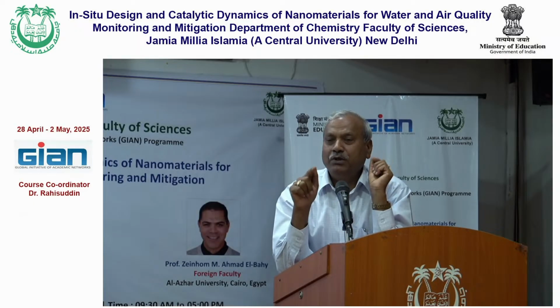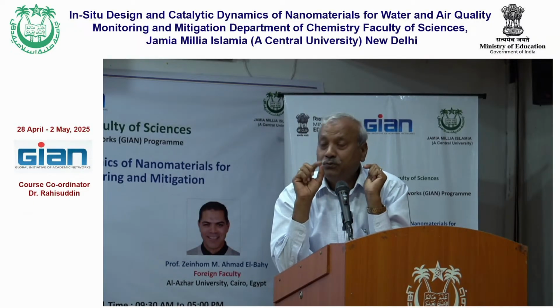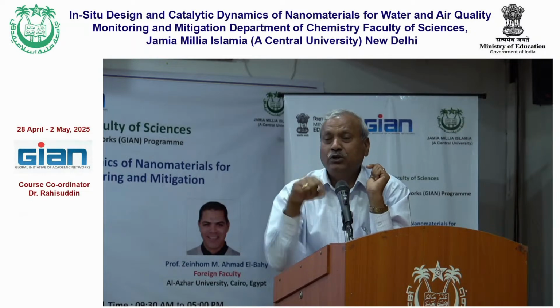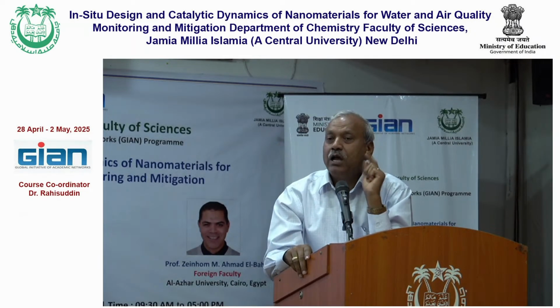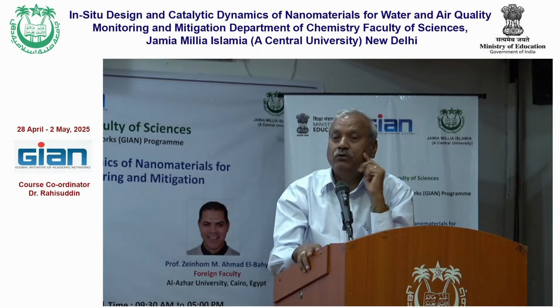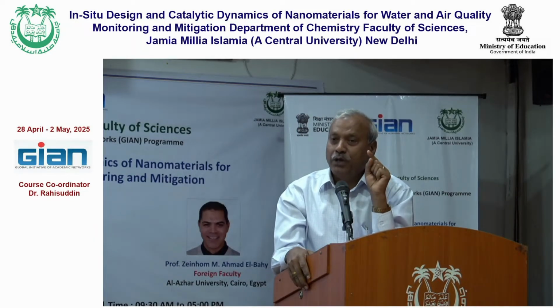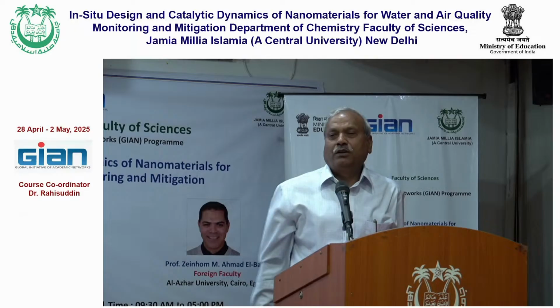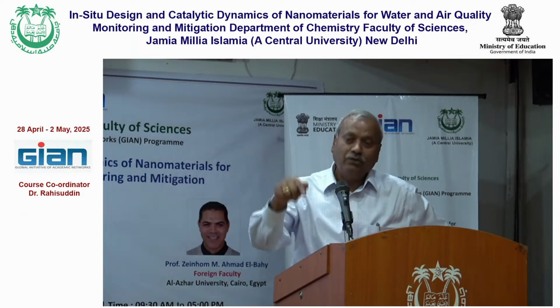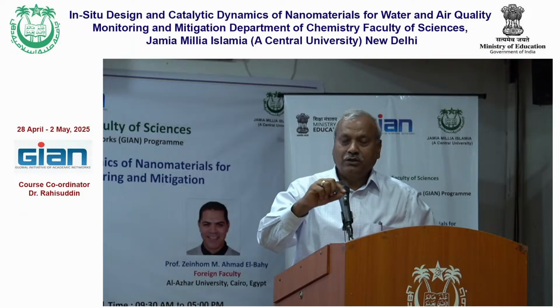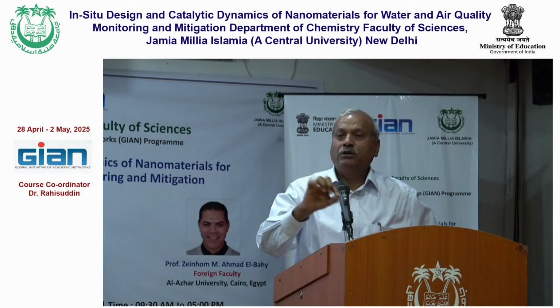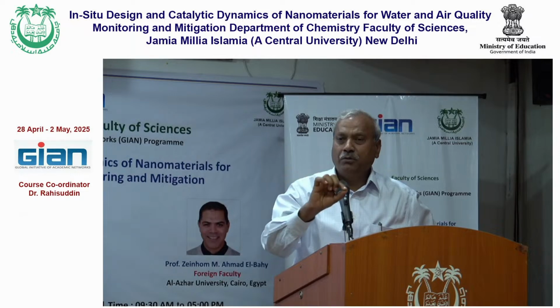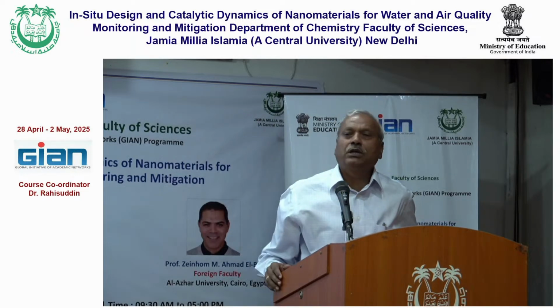So what is happening, actually, to your question, now coming back to the vanadium 4: when you add oxygen or an oxidant, it goes to 5 immediately, and it is doing the catalytic reaction. In some cases they come back to vanadium 4. So the vanadium 4 paramagnetic molecule is also equally active like your vanadium 5 diamagnetic. The only thing is it may be a little delayed, because when you are adding the oxidant, it is converting from 4 to 5. That much time it may require, so you may have some stagnation period. Ultimately, it gives you the same catalytic property.